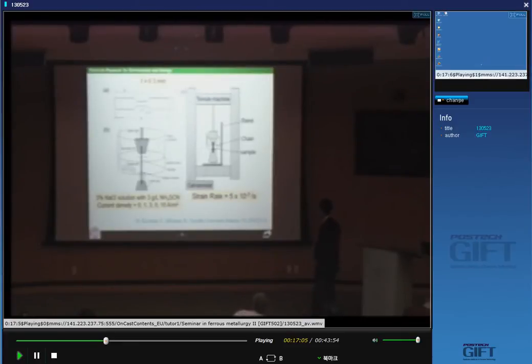I selected a low strain rate, 5 times 10 to minus 5th per second, to promote hydrogen effect. That means long enough time for hydrogen entry during testing. I pushed the charging equipment button, and then soon after that I started the tensile test.